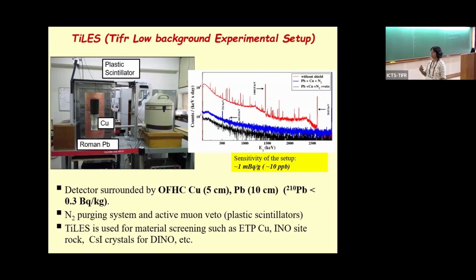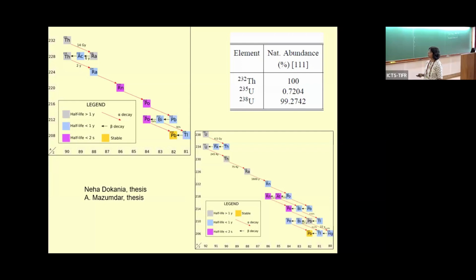In addition to that, the whole thing is enclosed in a Perspex box and we purge it with nitrogen to get rid of the radon, which comes from the uranium chain. And I'll show you how much change you see here. For example, this is the normal spectrum. The moment you put all this shield, the continuum has substantially reduced. And further, when you put the veto, the continuum is also reduced, but you also see some changes in the lines of interest.